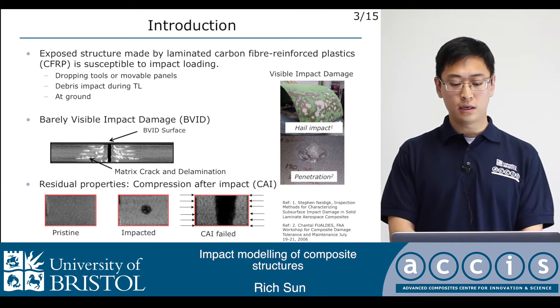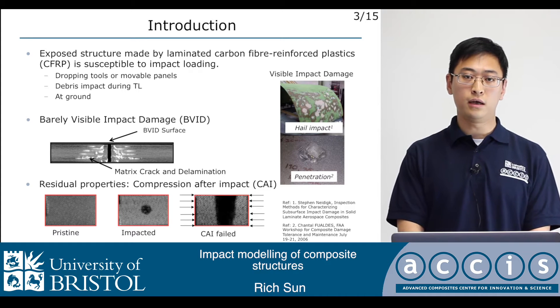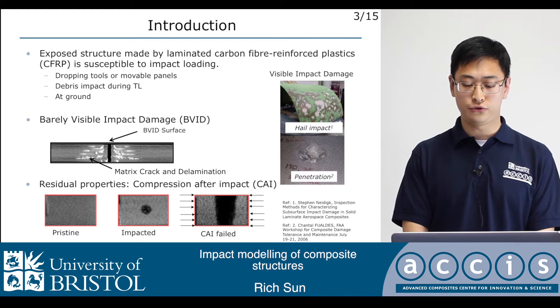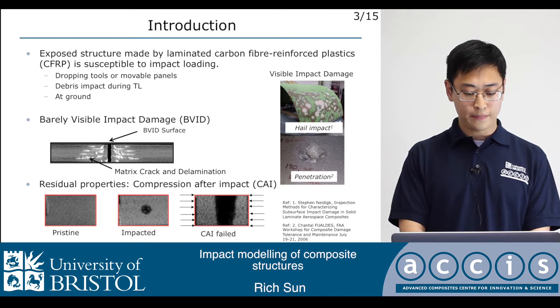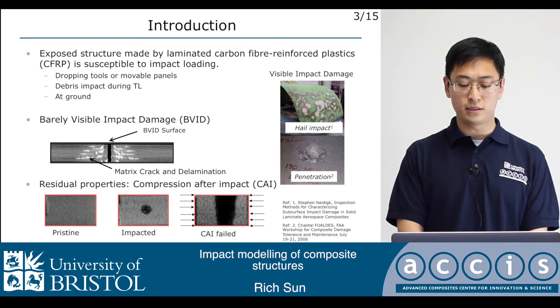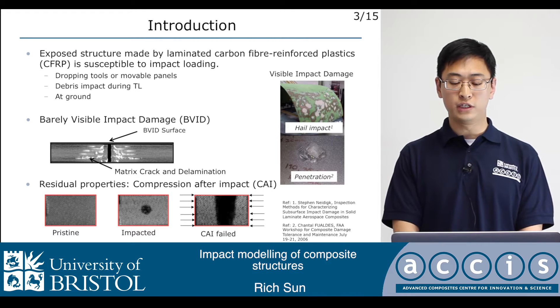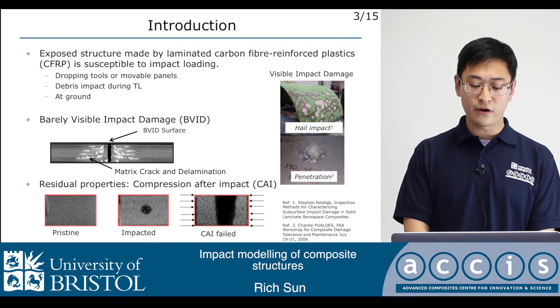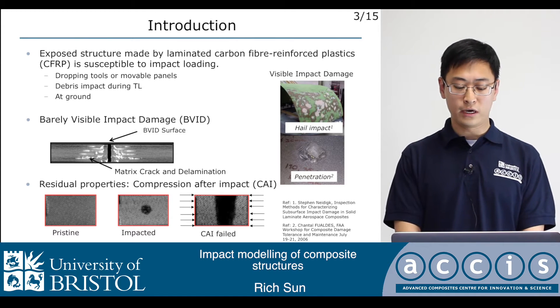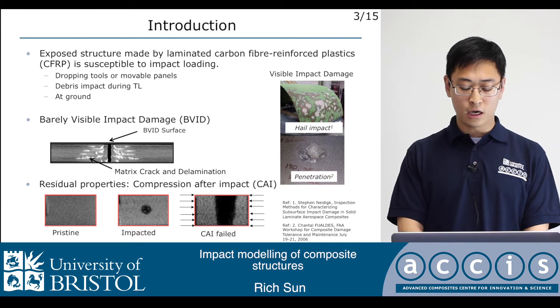Visible impact damage may leave little or nearly no physical indentation at the surface, making it very difficult to inspect during maintenance. Moreover, this kind of damage is easy to propagate under compression, so residual compressive strength reduction can be up to 40%. It is therefore very important from a design and certification standpoint to study the impact damage mechanism in composite structures.